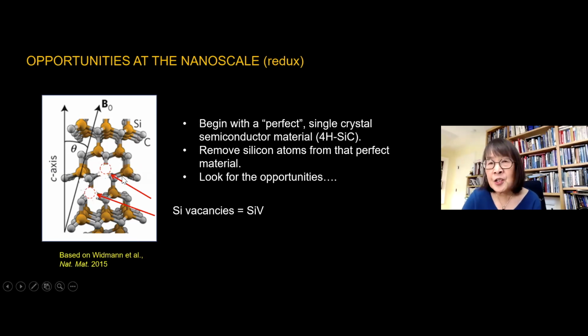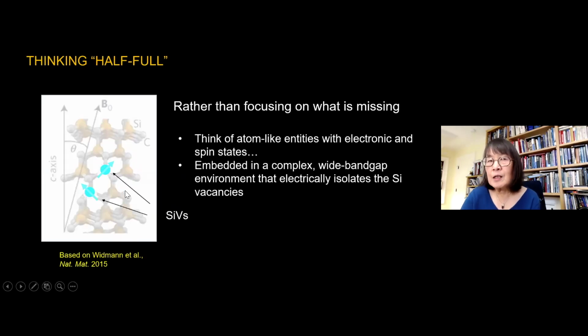The way I've presented this to you is that we're taking a perfect material and we're making it somehow less perfect. But if we were to take the half full rather than the half empty view of science, think of those vacancies not as something missing from the material. Think of those vacancies, surrounded by the electrons in the local atomic vicinity, as atom-like entities with particular electronic and spin states that in turn are embedded within a complex wide bandgap environment that in fact has used tremendous sophistication to actually electrically isolate these atom-like entities.